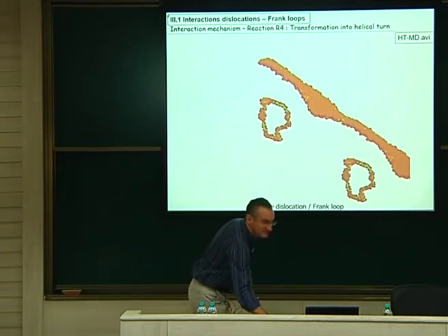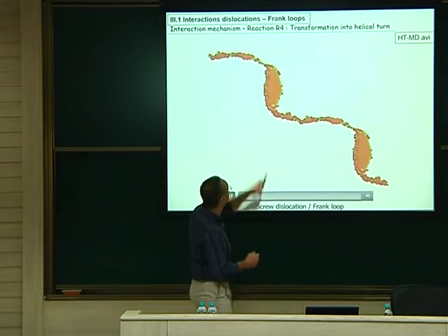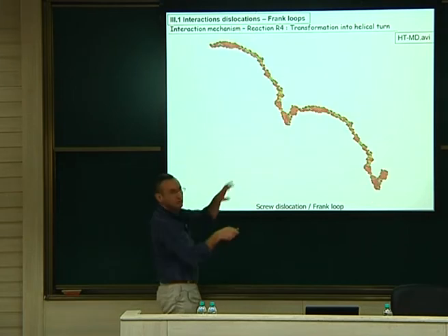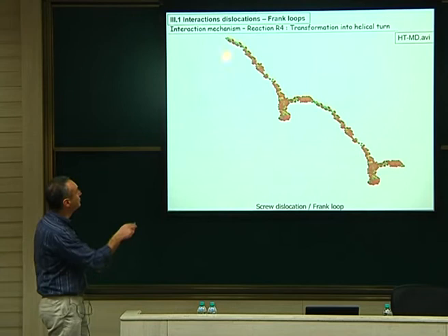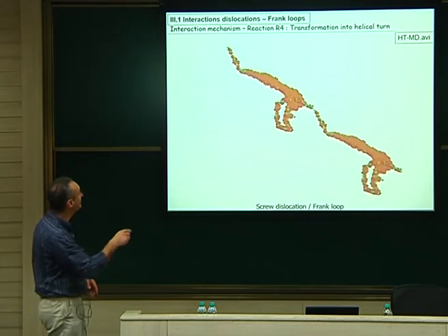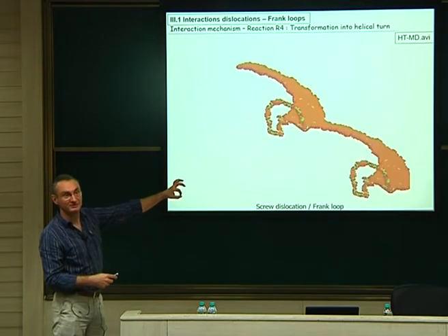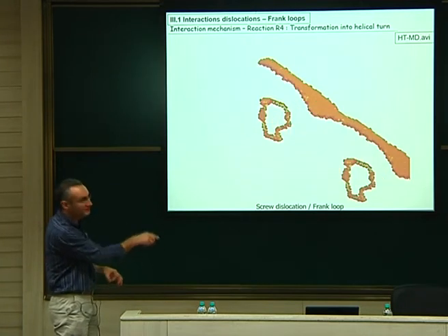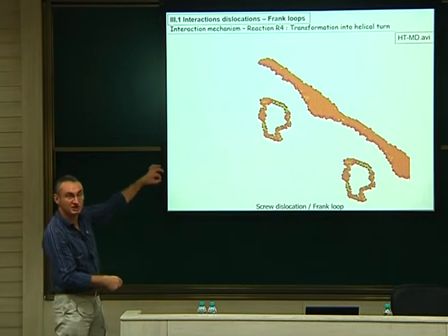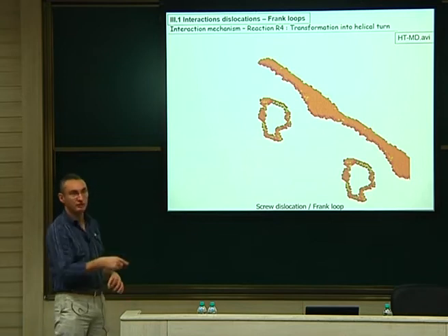So you had two sessile dislocations that were 1-1-1 loops, like this, those cannot move. Dislocation comes, you can play with the partial vectors and you will see that just because of the local recombination, you are able to form a perfect dislocation line, which is like a prismatic loop. This is a prismatic loop, actually, with the Burgers vector, which is like that. These are two prismatic loops, which are generated because of unfolding of the Frank loops.